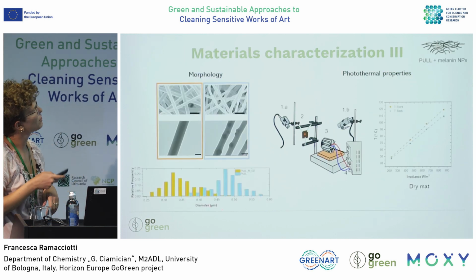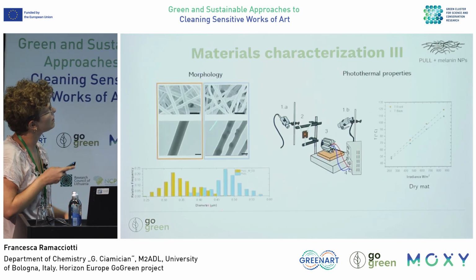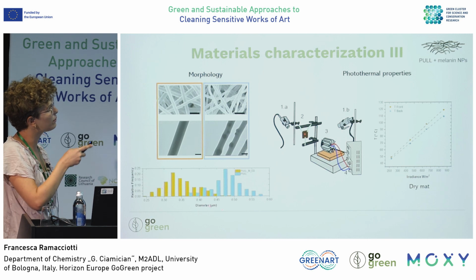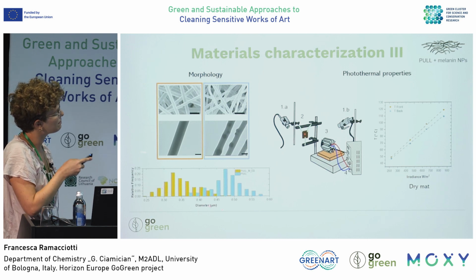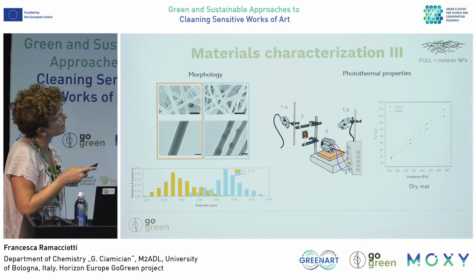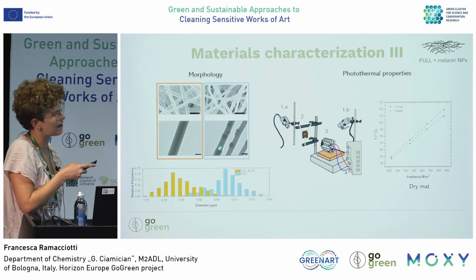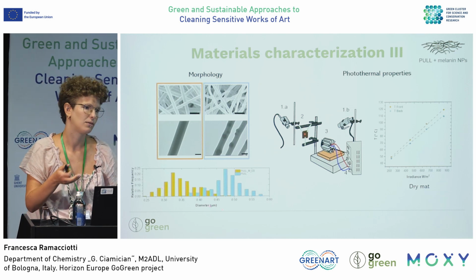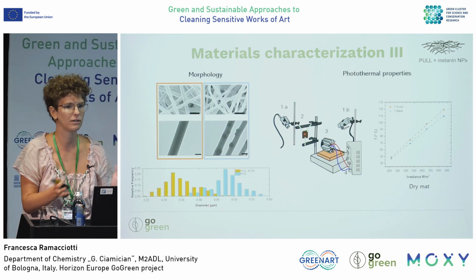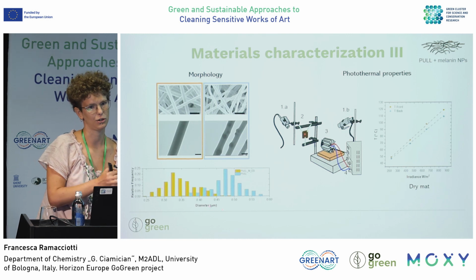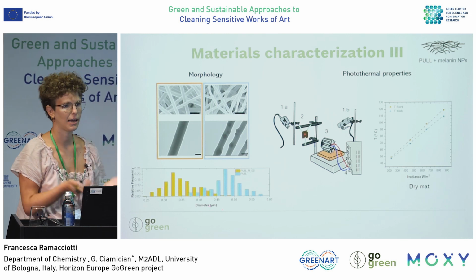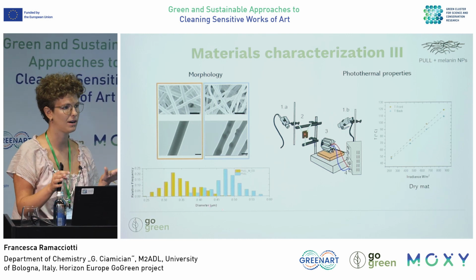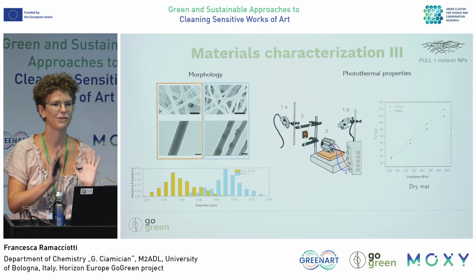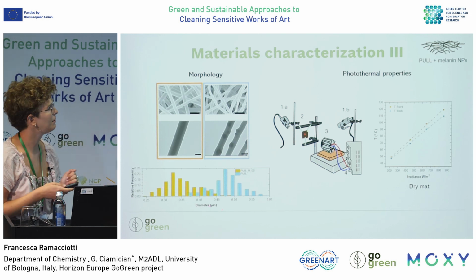So, of course, we started with the study of the morphology, and as you can see, this is plain pullulan, SEM and TEM pictures, and you can see that the nanoparticles are inside the fibers. This means, and we also performed some studies, that the particles remain confined in the tissue. So when you wet the mat and you apply it on your surface, you don't have release of nanoparticles, so you don't have risk associated with it.